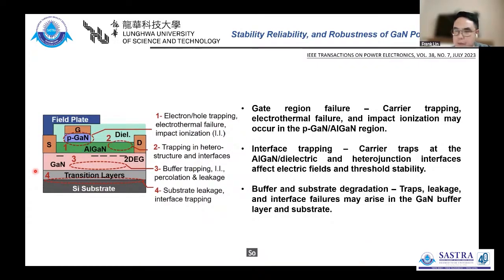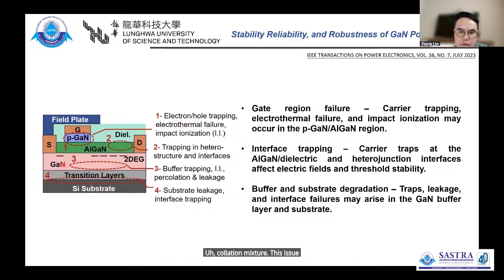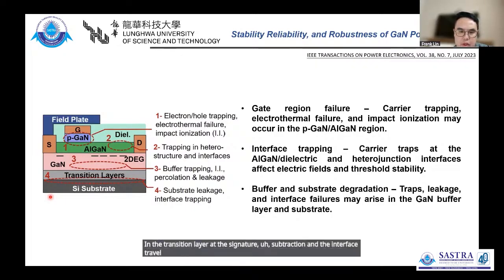So third, in the GaN buffer layer, possible failure mechanisms include buffer traps, impact ionization, and percolation leakage. These issues raise leakage current, causing localized overheating and reducing long-term reliability. Fourth, in the transition layer and the silicon substrate, leakage and interface traps may impair device isolation capability and breakdown performance, especially critical in high voltage applications.